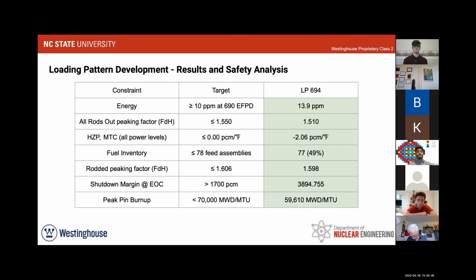For our safety checks, the first one we did was the moderator temperature coefficient. We want our moderator temperature coefficient to be negative to avoid any positive feedback loop in case of a positive reactivity accident. Our most limiting case for MTC was the hot zero power case at the beginning of cycle, and we actually got our MTC to be negative at negative 2.06 pcm per degree Fahrenheit. As for our fuel inventory, we needed at least 49 to 50% of our assemblies to be feed assemblies, and we actually met this goal with 49% of our assemblies being feed assemblies.